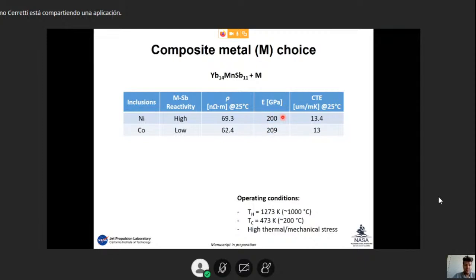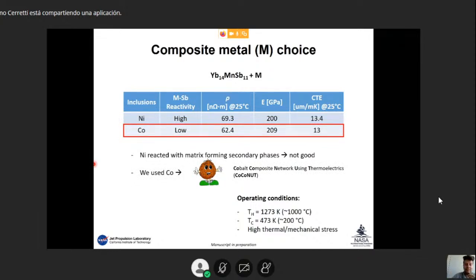The Young's modulus is about 200 gigapascal for nickel, with pretty good electrical conductivity, but the problem is that it reacted really badly with antimony. Therefore, we couldn't use it. Cobalt has very similar properties to nickel, but it has a lower reactivity with antimony. Therefore, we studied the impact of cobalt in the matrix, and so the project I was supervising was called Coconut, or Cobalt Composite Network using Thermoelectrics.